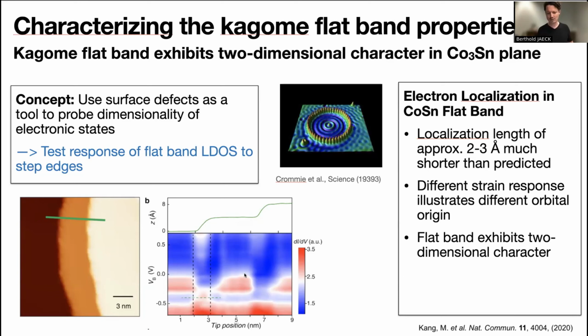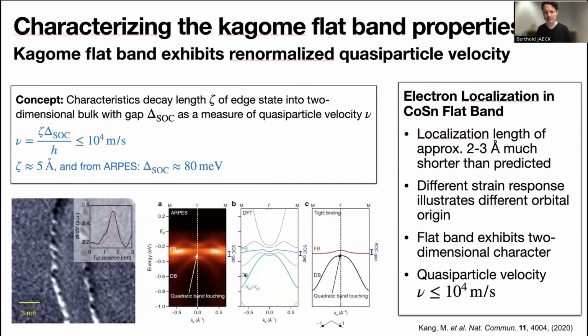Now, there has been quite some discussion about the topological character of this edge state, which people believe could be of non-trivial origin. Here we focus on using this edge state as a probe to determine the quasi-particle velocity of our flatbands. We know from ARPES measurements that at the gamma point, the quadratic band touching is lifted, and there's about an 80 milli-electron volt spin-orbit-induced gap between the flatband and the Dirac point. If we take this at face value and also investigate the spatial decay using a simple fit function, we can then directly calculate the quasi-particle velocity inside this flatband. Interestingly, we find this to be a little bit less than 10 to the 4 meters per second, which is a very small value.